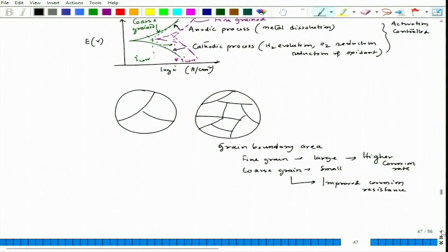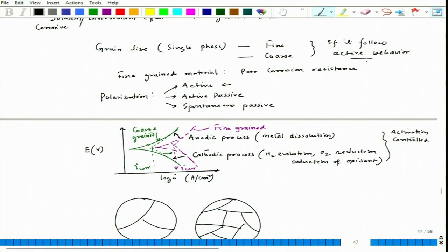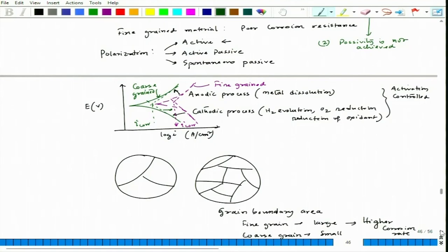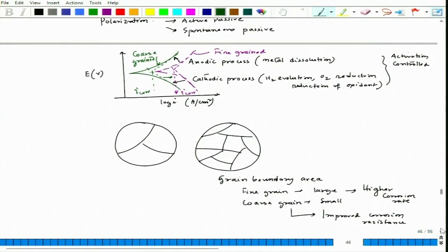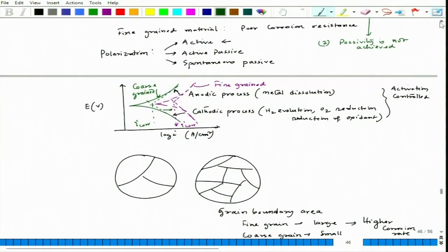But remember, that happens when the material shows active behavior all the time and does not achieve passivity. So we can add one more condition here. If we list down the two important factors, one is active behavior, and the second is that passivity is not achieved. So that time definitely the corrosion rate increases with finer grain size. Even if it is not activation control for both the processes, the anodic process must be activation controlled. Then only with finer grain size do we have a higher corrosion rate.